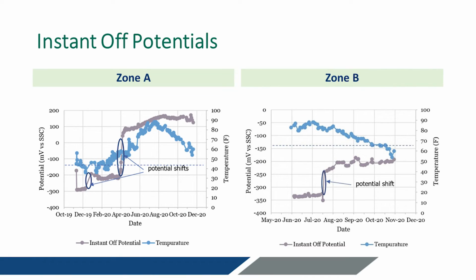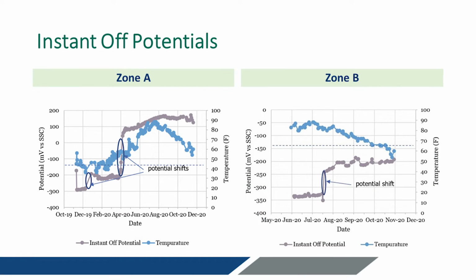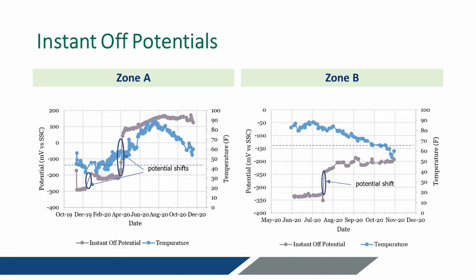And so this is kind of what the performance looks like, and I'll talk just a little bit about what we're seeing here. There are reference electrodes embedded in the concrete. So what you're measuring is the potential of the steel and how that's being affected by the anodes. And so really when you first install the anodes, the steel is in a corroding state or near corroding state. So the potential is rather low, negative 300, negative 350. Anyone who's familiar with corrosion potentials knows that around negative 350 is where corrosion is 90% active. And then as the anodes start to polarize, effectively electrochemically changing the environment around the steel, the potential of that steel will start to change, and you can see that the steel potential starts to move more electropositive, which is in the passive direction.